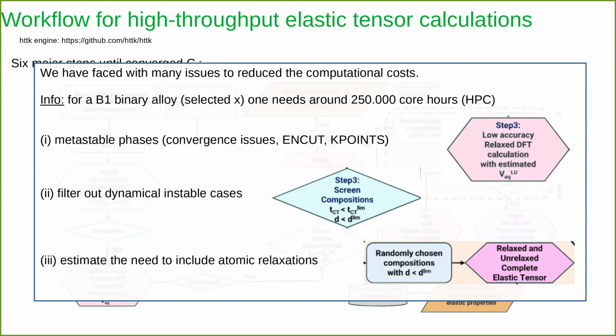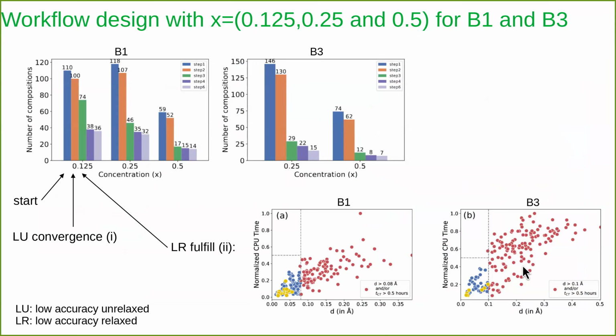Here we do a filtering: we allow only a certain time limit and a certain maximum displacement. If it goes beyond a certain displacement, then we say that we don't focus on this alloy further in the workflow. If a certain alloy which we have selected passes this stage, then it can go into the situation where we calculate the relaxed and the complete elastic constants for that composition. So here you can see an example so that you get a better feeling about what's going on.